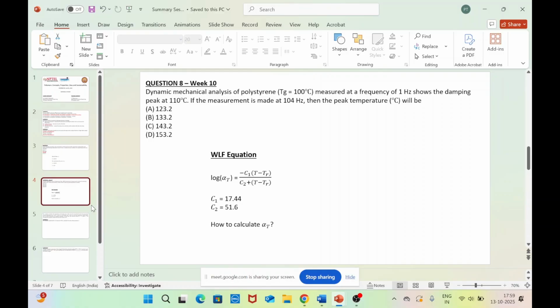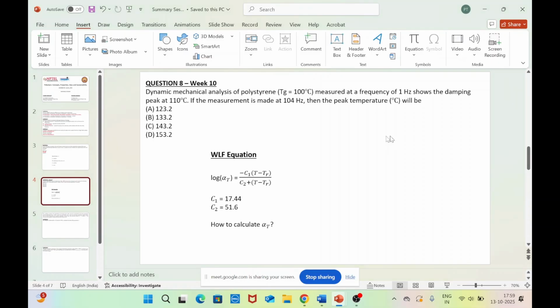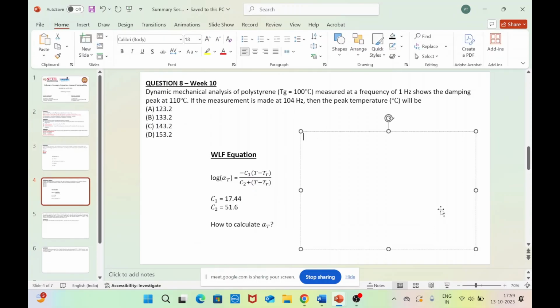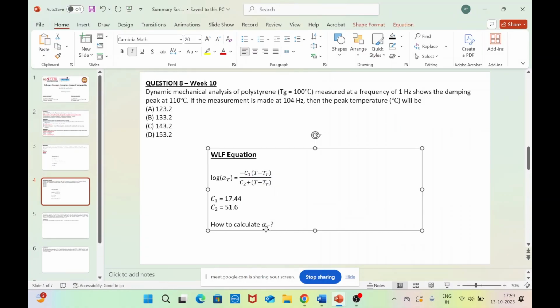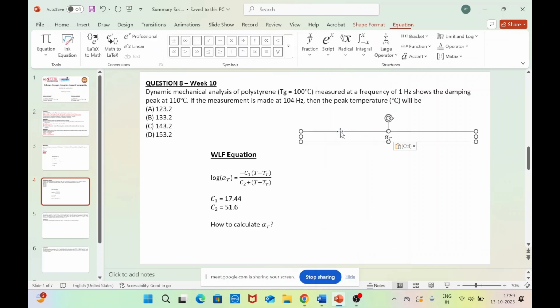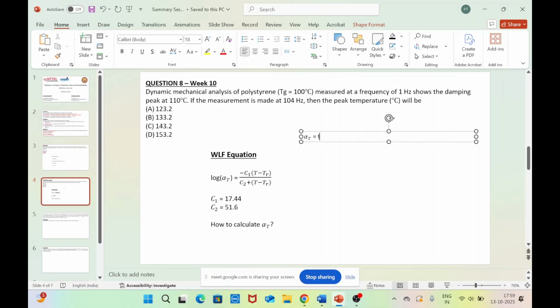So can we write it this way? Alpha T, that is your shift factor, can actually be expressed in this form as well. Alpha T equals F by Fr. So that is the frequency at which you are going to measure to that of your reference frequency. So here our reference is basically based on that damping peak observed at 110 degrees Celsius.